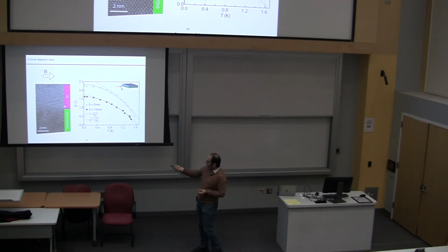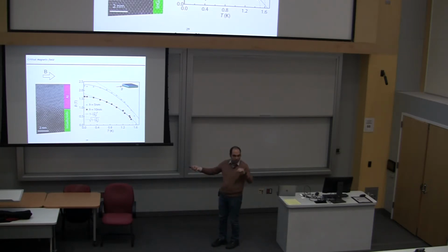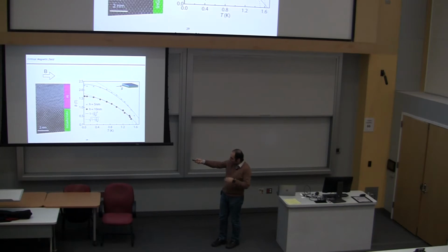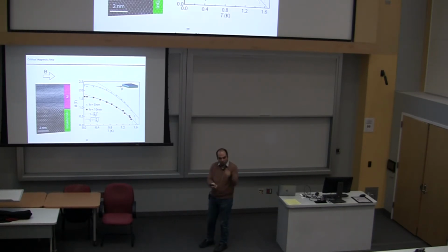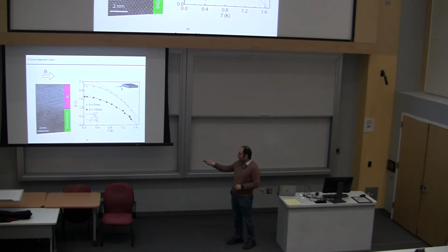So we did that. This is the magnetic field being applied in-plane, the plane of the aluminum, and this is the magnetic field as a function of temperature, right? So first, if your aluminum is bulk, very thick, the critical field is here, Tc is here. So Tc is 1.2, and the critical field in this graph is exactly 0, right? So when you make it thinner and thinner, things just start to happen. The first thing is that the Tc gets pushed up. So here you can see it's like 1.5 Kelvin at 0 magnetic field. And as you increase the field, this number goes up. At the lowest temperature in the dilution fridge, you can get about 1.5 Tesla, which is pretty good, right? We needed half a Tesla. And if you make it even thinner, 5 nanometer, then the Tc gets pushed higher, around 1.6 Kelvin, with a critical field of about 2.25 Tesla.